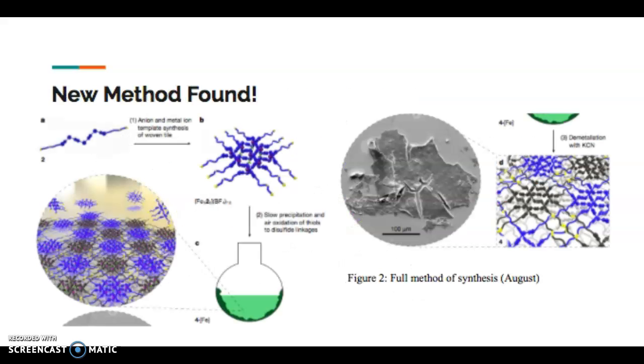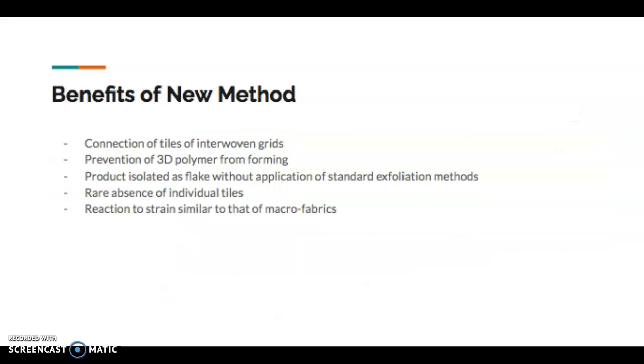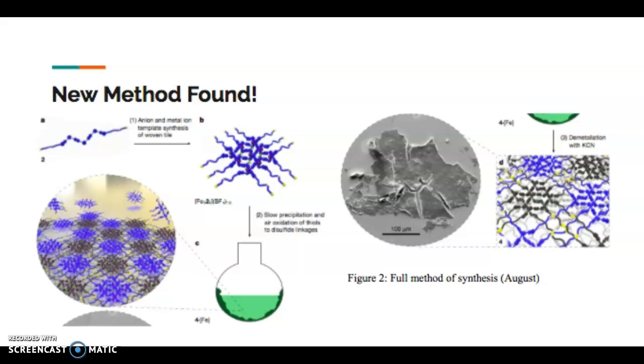The offset layers and anions and bulky isopentyl groups between grid layers prevented strand connections between the layers so as to not make a 3D polymer form. Although there may have been some disulfide linkages, those were insignificant. The product was able to be isolated as a large, very thin, flaky nanosheet, even without standard exfoliation methods such as manual grinding or sonication. As you can see here, there's the very nice flaky nanosheet.